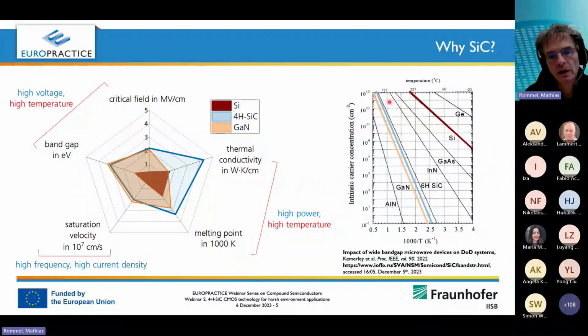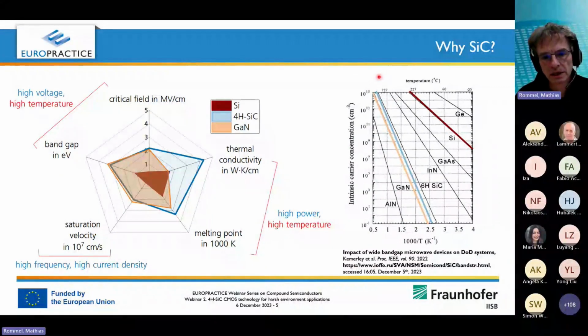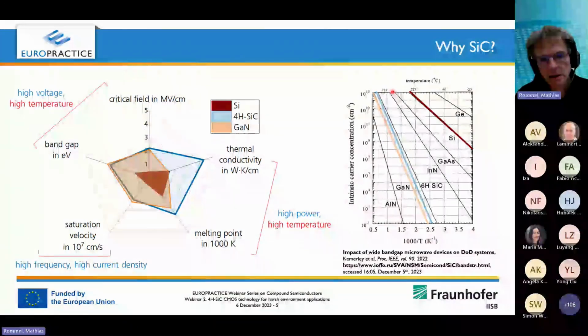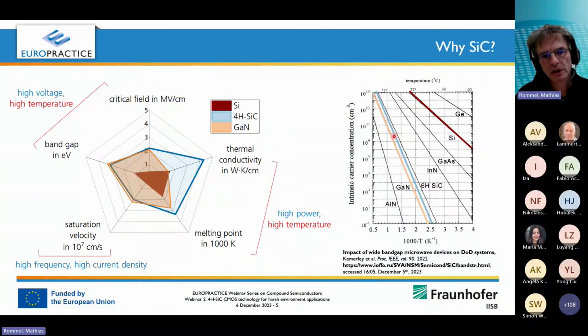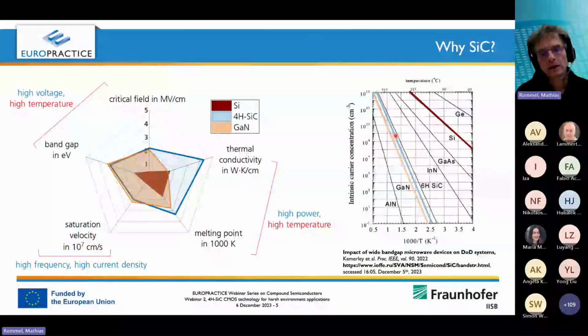If we, however, look at the 4H silicon carbide here in light blue, you can see that we reach this level of intrinsic carriers just at very, very high temperatures, above 700, 800 degrees Celsius. And that's why, for example, if we go to 600 degrees Celsius, which we aim at, you still have a very, very low intrinsic carrier concentration. And that's why you can, in principle, just from the basic semiconductor material point of view, use this material for very high temperature applications.